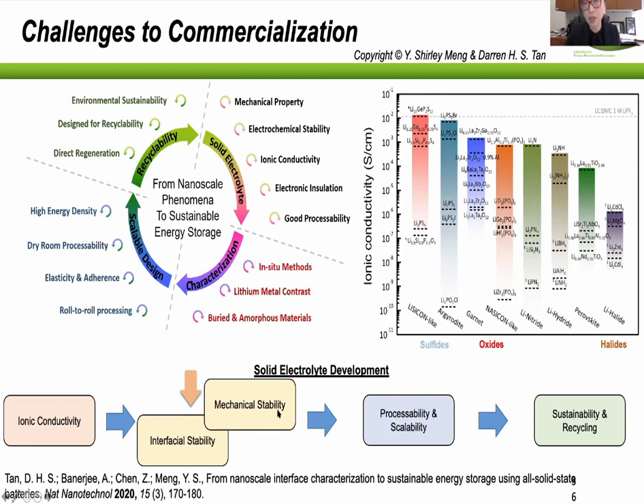So that opens up a lot of electrolytes. Interfacial stability and mechanical stability, particularly mechanical stability, I feel like I just started understanding, because of the lithium metal, you are in the solid state. There is so much fundamental science not understood here. Now, the next step is processability and scalability. I think for me, it's a big question mark. So far, the only material that can give me 1 kilogram scale is the argyrodite lithium phosphate sulfide with chlorine doping. That's the only one I can easily get a kilogram quantity of. None of the others give me a kilogram for less than $1,000 to $2,000. Even for argyrodite, I'm paying $2,000 per kilogram, right?